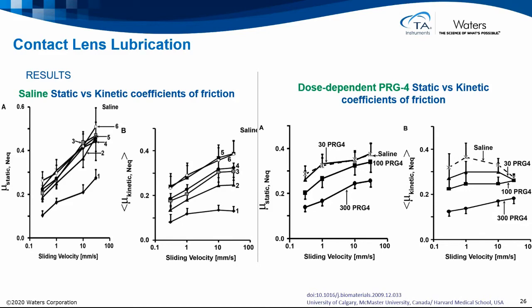On the left plots, we've got static friction and kinetic friction, and the different curves are the number of times that the shearing is happening. The first time we get a low number, and that's good, you get low friction, but then as you pass by that same material again, you repeat that motion, the friction goes up and up and up, the static friction. The dynamic friction also goes up, a little less bunched, but also goes up. So you can see sliding velocities again on the x-axis, and then the first pass, second pass, third pass,